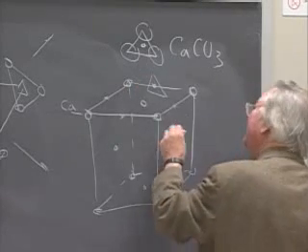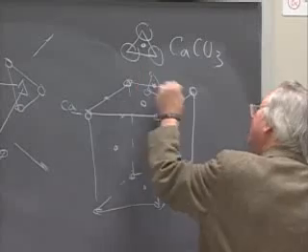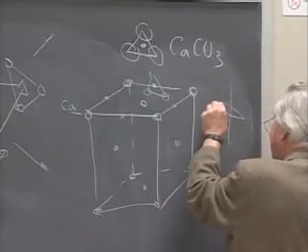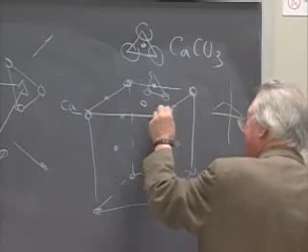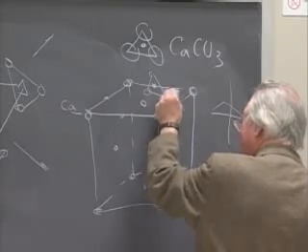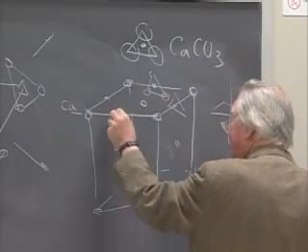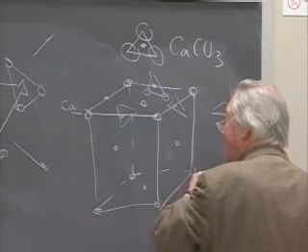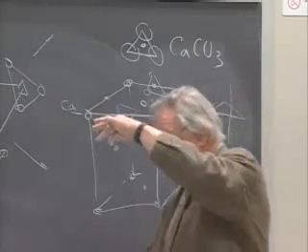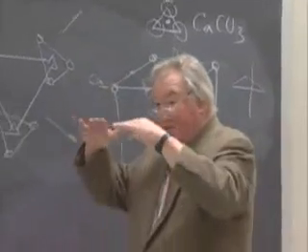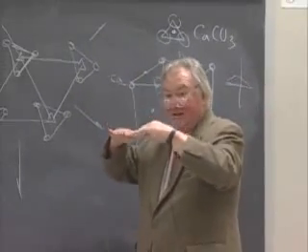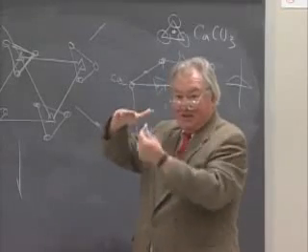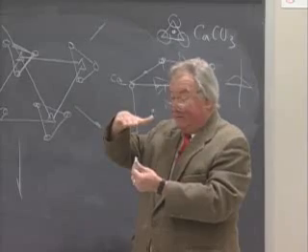These triangles are normal to the body diagonal of the cell. So you have one family of triangles that are all parallel to one another. On the next edge, the triangles are anti-parallel to this first orientation. So think of rock salt, tip it up on its body diagonal. Every place you have a chlorine anion, place a triangle in an orientation that is perpendicular to the body diagonal of the rock salt structure.